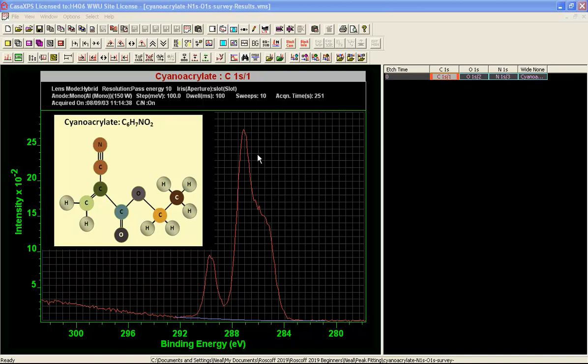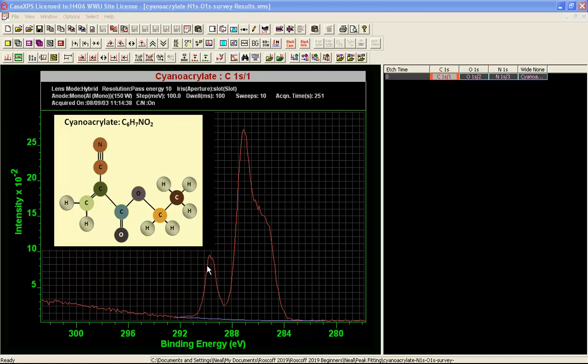So we need six component peaks and we will use this model here at least in the first instance to construct this peak model and then perhaps add one more to represent the signal that doesn't belong to this kind of structure. Now there is an element of guess work here because we really don't know how these peaks all form beneath this envelope here. But the best one we can target will be this first one here. And that would correspond to carbon double bonded to oxygen and single bonded to oxygen. And that would be the binding energy or the offset of the binding energy relative to these other peaks that suggest that this peak is in fact this carbon atom here.